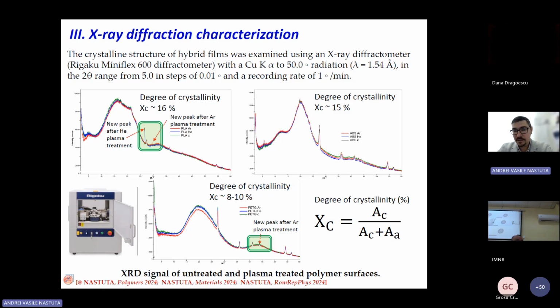So if the material is more crystalline, then we need a higher temperature to melt the polymer. In our case, if it is more amorphous, the temperature of melting the polymer is lower. This helps us in making an estimation of the energy consumption of a 3D printing process. So if the material is easy to melt down, and we have a 3D printing farm of, let's say, 100 3D printers, then the consumption of energy to build some plastic object with this printing farm is lower, so it is more effective.